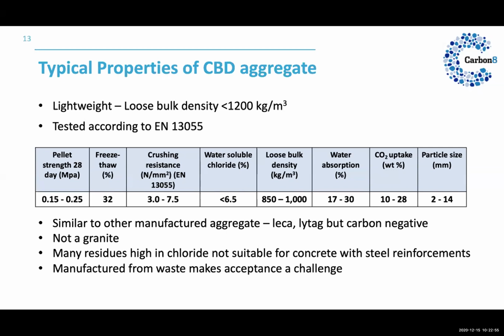These sorts of residues are also high in chlorides, and so you have to be careful about their use where there's concrete with steel reinforcements. And so the other thing is that because they're manufactured from residues, and the legislation around the residues varies by state in Europe, the acceptance of them as a product is a challenge and has to be negotiated through each state.